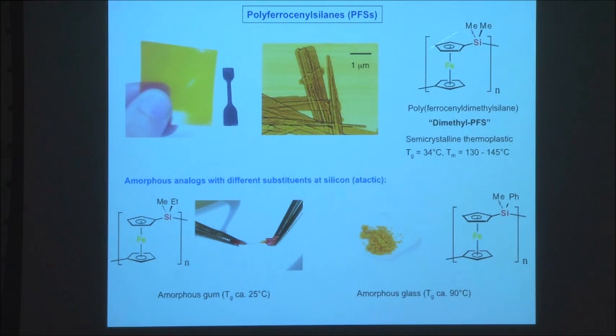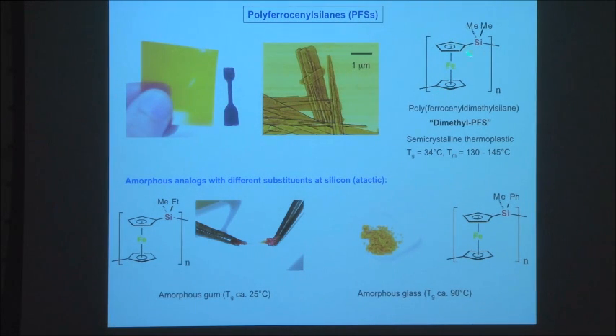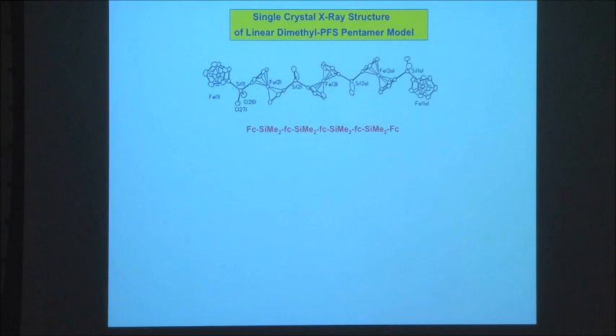So in the block copolymers that I'm going to talk about, at least in the first part of the lecture, the core-forming block that will crystallize will be based on this block here with 2 methyl groups on silicon. So how does this polymer chain actually pack in the solid state? It's an interesting polymer chain. You've got ferrocene here with these 2 5-membered rings, an iron sandwich here, and you have this silicon spacer between the repeat units. To get some information on this, we made a model pentamer and crystallized it. We got a single crystal X-ray structure for this material.